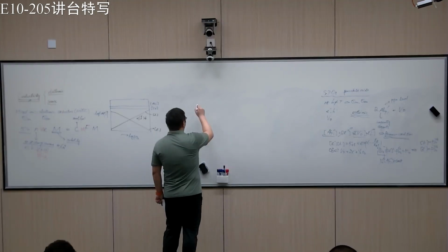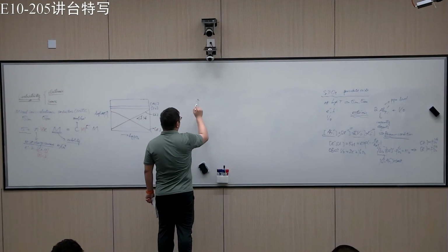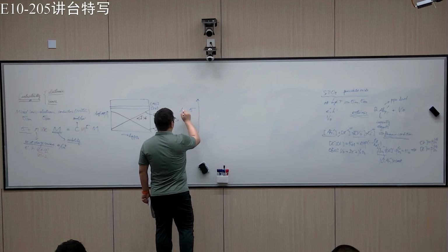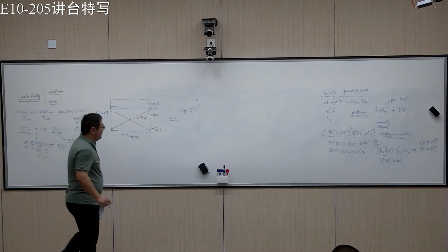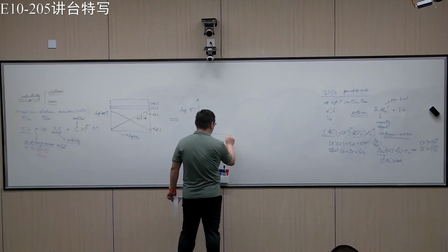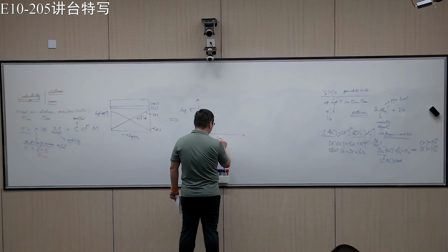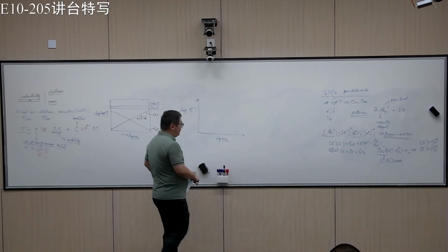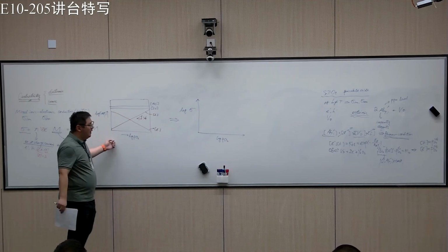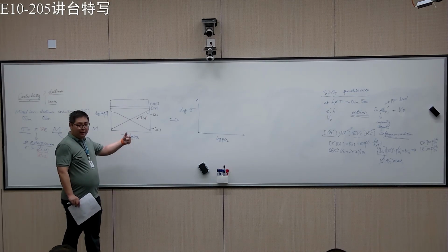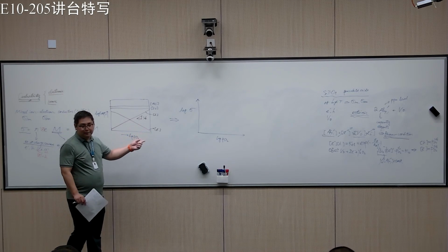Here we want to know the conductivity or log conductivity, I mean, it's the same thing, right? As a function of the driving force, basically log pO2. So if you think about it experimentally, you take a particular sample and you control the pO2, then you measure the conductivity, and you basically construct such a plot.